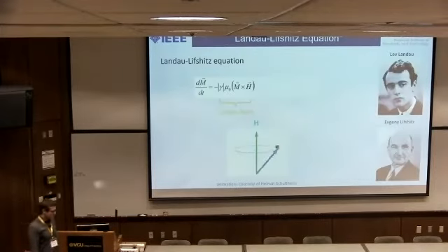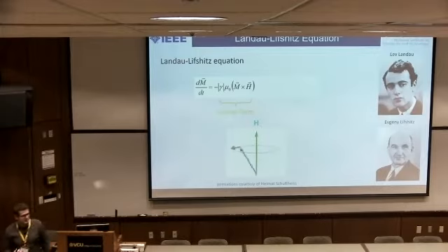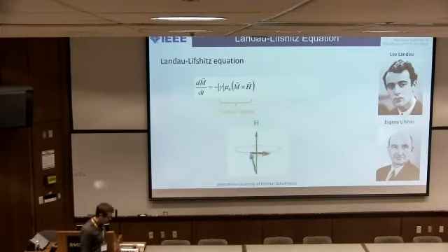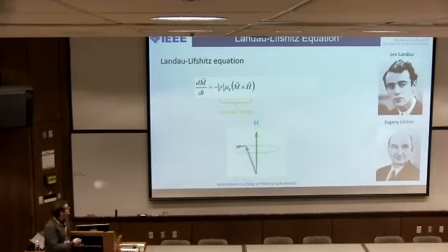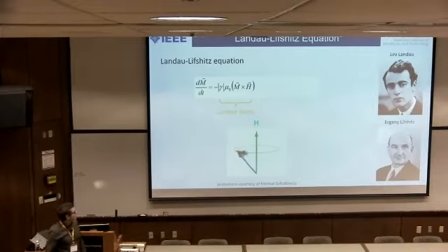Those dynamics are usually described by what we call the Landau-Lifshitz equation. This is an equation that was derived in 1935. It wasn't actually derived for what we use it for today, which is to describe these dynamics, but was originally derived to explain domain wall motion, because FMR wasn't actually discovered till the 50s. It's a simple classical torque equation. It consists of 2 components. You of course have the time derivative of magnetization, but you have this torque here, which is what we call the Larmor term. That describes the precessional motion given by this cartoon right here.